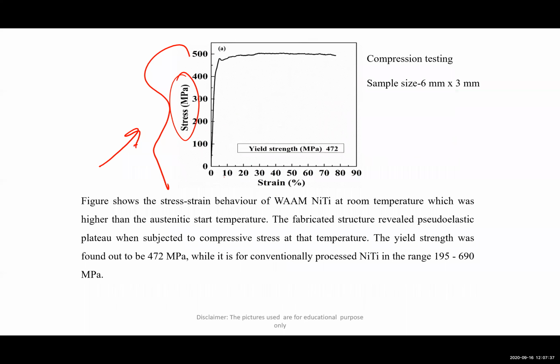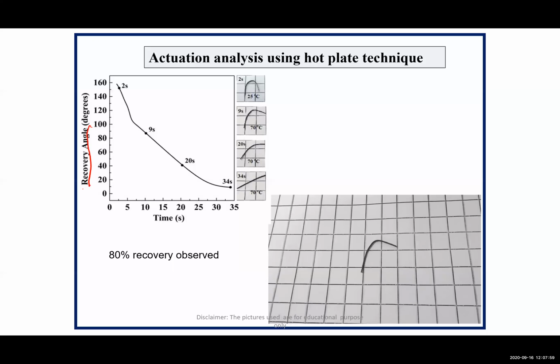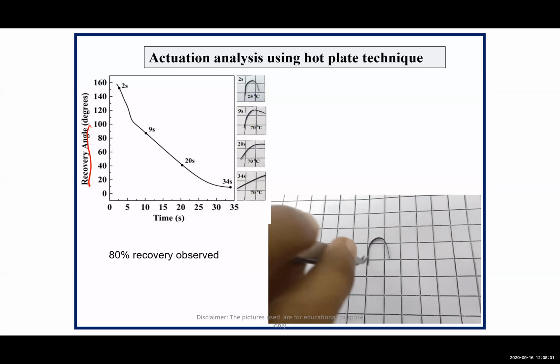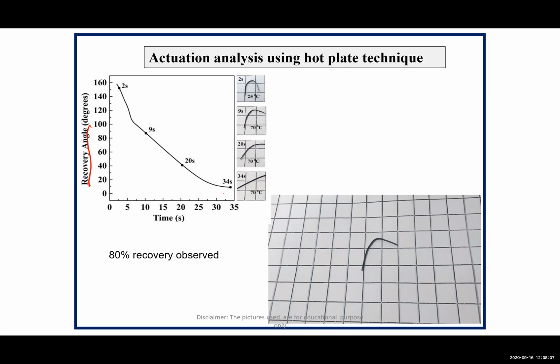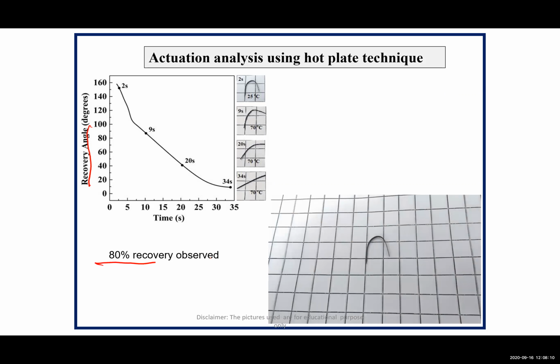In order to study the actuation characteristics, we used a concept called recovery angle, similar to the thin film. In this thin film, we went for different time variations and studied the recovery behavior. Almost 80% recovery was measured with the as-manufactured shape memory structures.